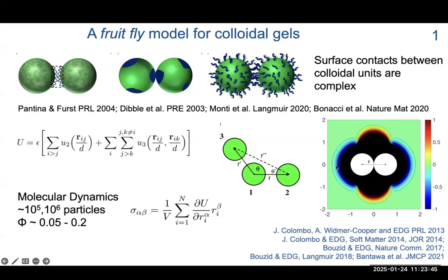So it will tend to bind more along this direction, and it will have to pay some price to bind along this direction. And this is basically to reproduce the fact that I was saying that in this system there may be some difficulty to form compact aggregates because the particles cannot necessarily do this, or there is some cost to pay to do this. And these tend to favor structures that are elongated in the way they grow, which then seems to be an important aspect in the formation of gel systems.